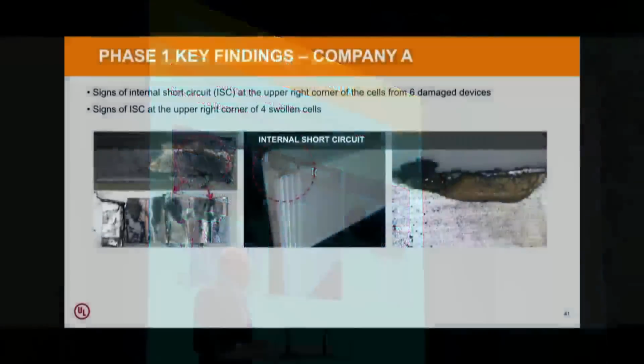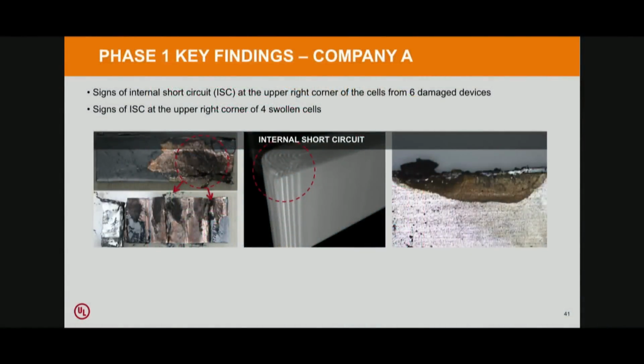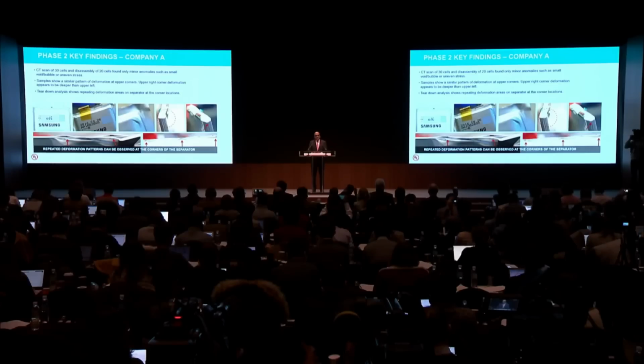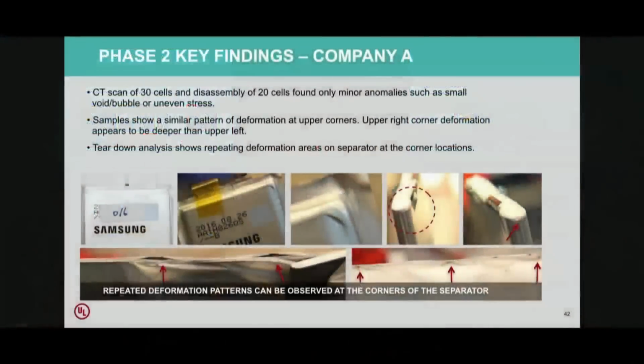There were signs of internal short circuit on the upper right corners of the cells from 6 of the damaged devices. And we also find internal short circuit at the upper right corner of 4 swollen cells within those damaged devices. For phase 2, we conducted a CT scan of 30 cells and did disassembly of 20 cells.